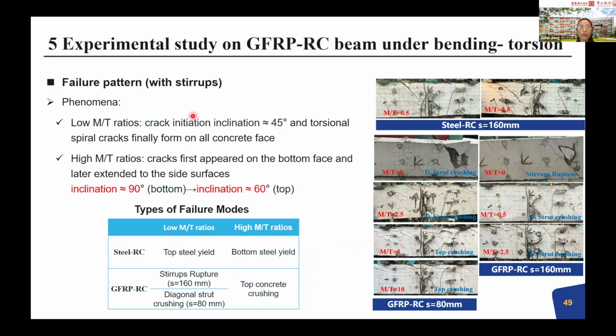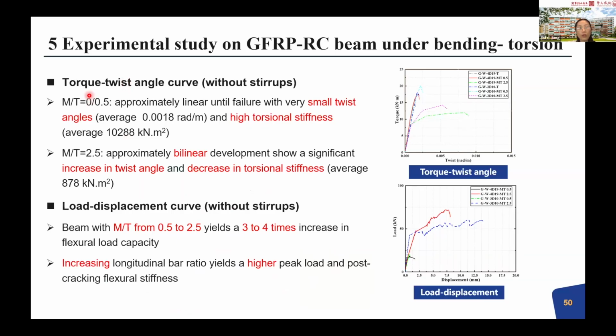Previously this was for beams without stirrup, and for beams with stirrup, the phenomenon is similar. The only difference is that we find more complicated failure modes for the FRP-RC beam. That is, stirrup rupture can be observed, and also concrete compression can be observed for lower moment torsion ratio. For higher bending control, there is also top concrete crushing, like what we've observed in the flexural design behavior of FRP-RC beams.